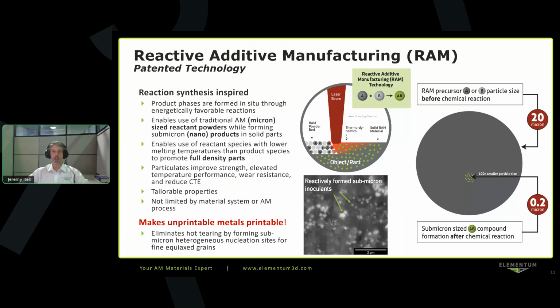So we're working with reactants that can then melt and dissolve into the alloy systems and then precipitate out very high temperature nanophase precipitates to provide the dispersion strengthening and inoculation. Particulates also improve the strength, the elevated temperature performance, wear resistance, and can reduce the coefficient of thermal expansion of those alloys. So you can use the type and the amount of those product phases that you're forming to control your properties, leading to tailorable properties.